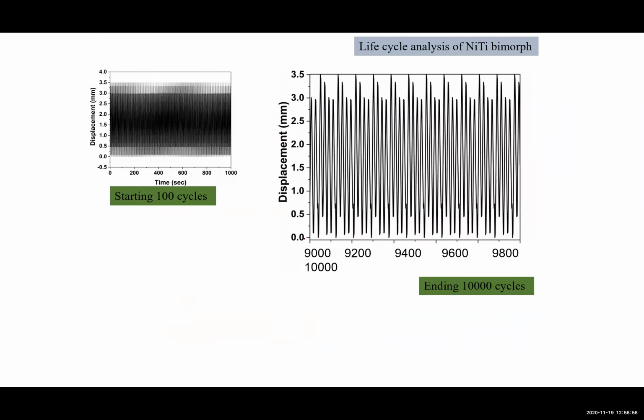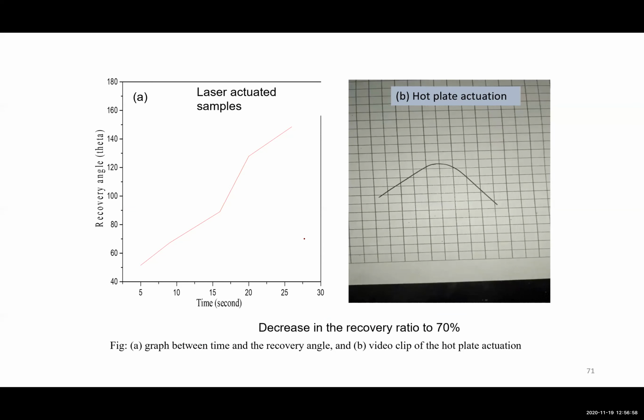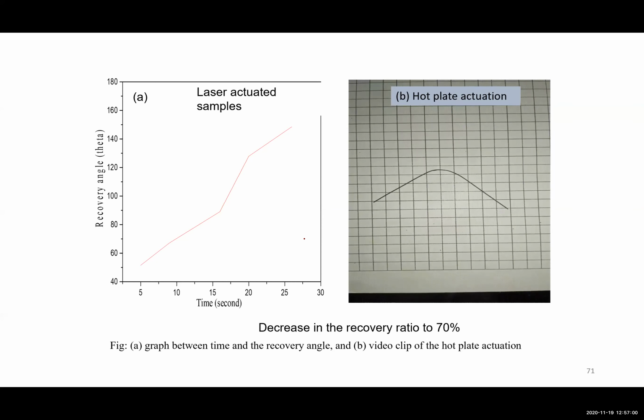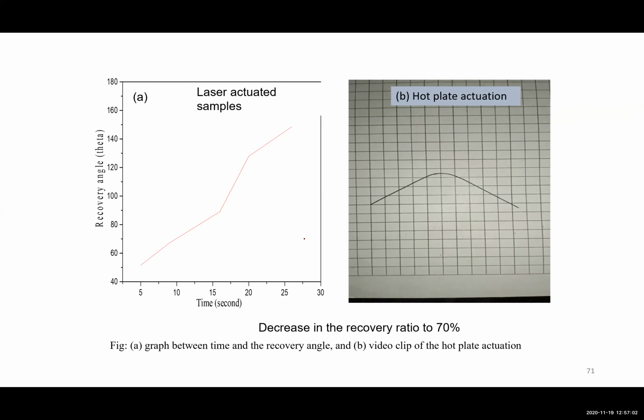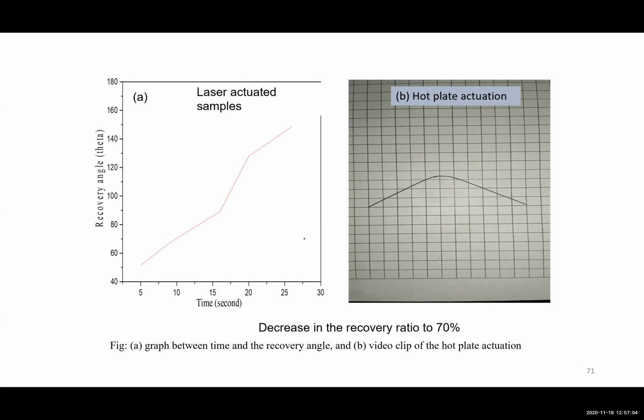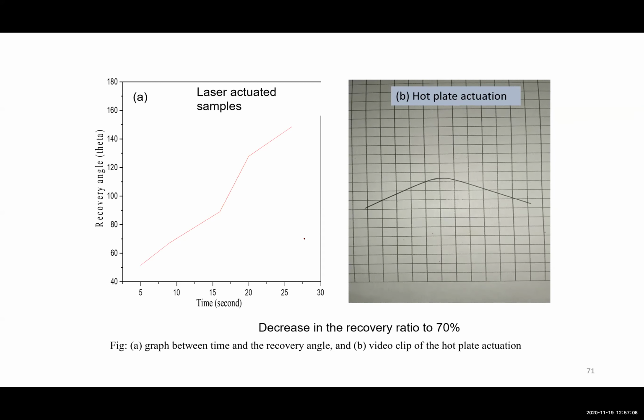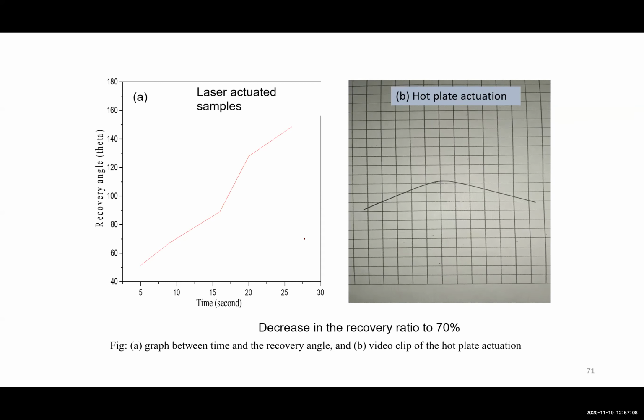Okay, so in order to test that, we took the laser actuated sample and went for a complete actuation analysis, and we observed that the recovery ratio was not changing much. In fact, there was a change in recovery ratio from 80 to 70% value, which was comfortable enough.